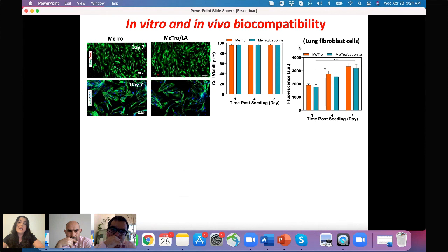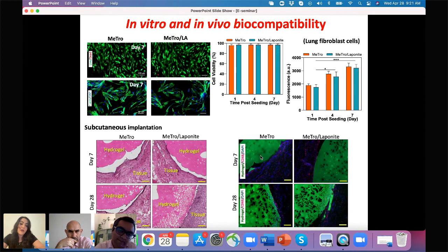We culture human lung fibroblast cells on the surface of this sealant. And then here we confirm that the cells remain viable on these biomaterials. They can spread and also proliferate and have proper metabolic activity as we culture them on this substrate. We also did subcutaneous implantation. Both formulations, Metro with and without Laponite, were implanted in rats subcutaneously. And then we show that over time, the hydrogel can degrade, it becomes more porous, and we observe tissue infiltration and cell infiltration inside the implant. We also didn't observe significant inflammation around the implant for both formulations, Metro and Metro with Laponite.